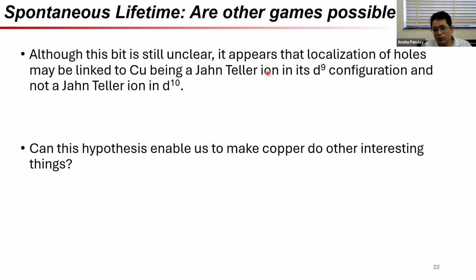And the reason why it might be linked to copper is that copper is an infamous Jahn-Teller ion in its D9 configuration, but not in its D10 configuration. So when we start off, copper is always in the D10, but it's likely that when the hole collapses, it's probably doing it on a copper which has gone D9. And this might be the entire reason why this material is doing whatever it's doing. It's of course a hypothesis, completely unproven, but can this hypothesis actually help us make copper do other interesting things? And that's an open question.